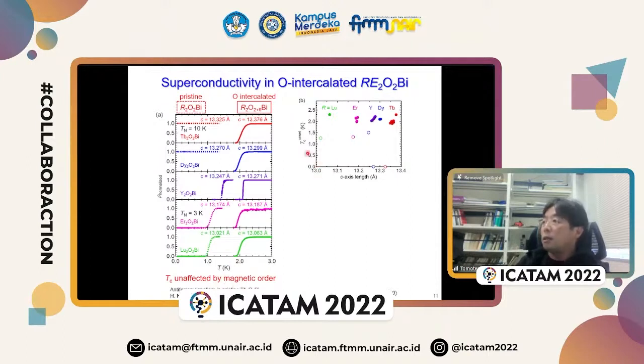And this is a summary of the superconducting transition temperature. The superconducting transition temperature is always around 2 Kelvin by oxygen intercalation. For all of these compounds, the C-axis length is different, but by oxygen intercalation, the C-axis length increases. And finally, the superconducting transition is obtained like this.